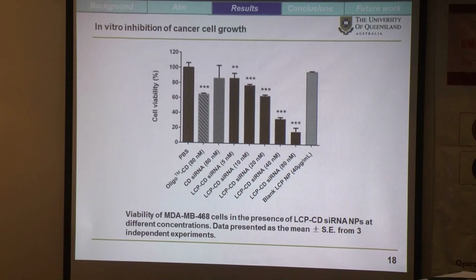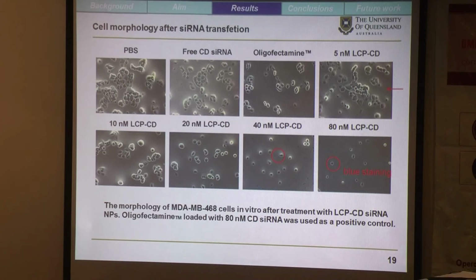At last, in order to preliminarily test the anti-tumor effect in vitro, the cell growth inhibition was tested on the human breast cancer cell line MDA-MB468 with siRNA. As shown in the figure, the cell viability is siRNA dose dependent, and as a comparison, the commercial delivery agent, Oligofectamine, can kill about 40% of the cancer cells at the siRNA dose of 80 nanomolar. At the same siRNA dose, our LCP nanoparticle can kill about 83% of the cancer cells, with a much higher inhibition effect than the commercial transfection agent. The morphology change and much fewer cancer cells in the LCP-CD siRNA treated group also confirm the cell growth inhibitory effect.